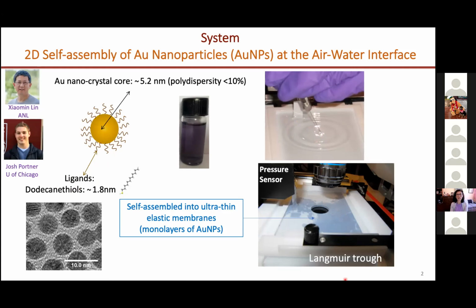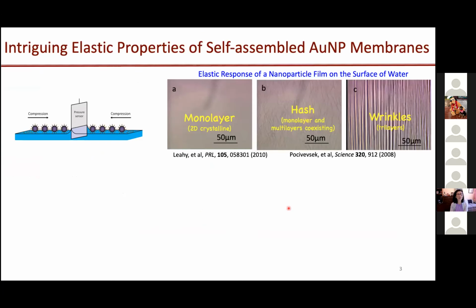And these monolayers have exhibited really interesting elastic properties at the surface of water. What we found is that when we spread them on the surface of water and compress sideways, the monolayer will change, buckle into multilayers, and eventually wrinkle, behaving just like a piece of plastic sheet.